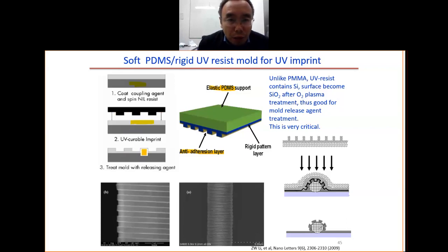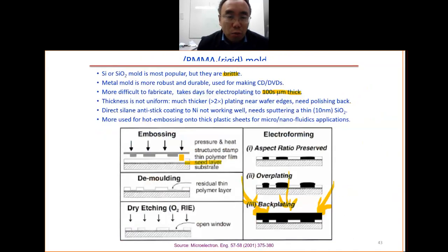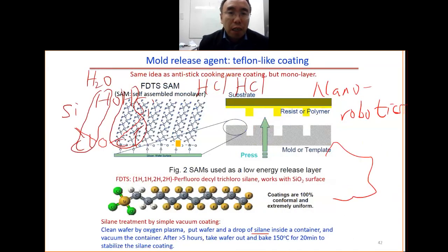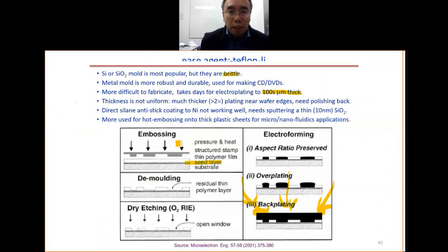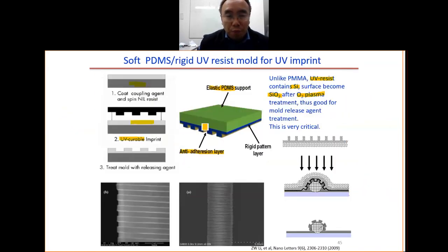So here the mold material is the UV curing resist. We know that the UV resist contains silicon, has lots of silicon inside. Then if we do the oxygen plasma treatment, the surface will become silicon oxide. When the surface becomes silicon oxide, you can do this process to make it a low surface energy for imprint. That's why this is a very good mold. That's why it's published in Nano Letters, a very good journal.